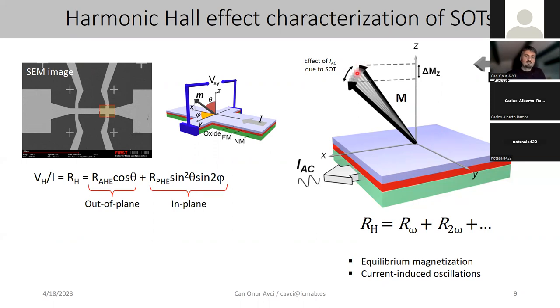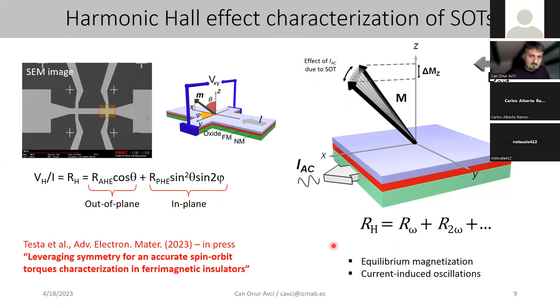These oscillations can be detected by using a second harmonic detection method, and by doing some analysis using both the first harmonic signal, the Hall effect signal, and the second harmonic Hall effect signal, you can get an exact number of values in a given system. This has been well established since 2012, 2013, since my PhD times. But just very recently we published a paper, you can also find it on arXiv, showing that this kind of spin-orbit torque detection can be adapted to systems with very small Hall effect response, without getting disturbed by experimental noise or by some spurious thermoelectric effects. So if you are curious about it, you can go check this paper.